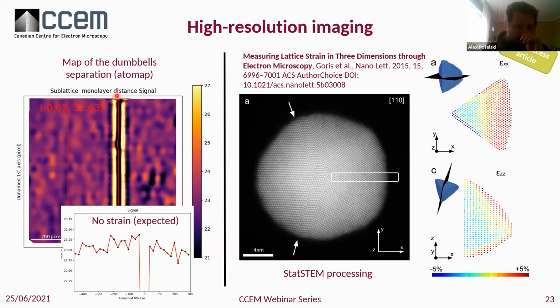On the other interface, this seems to be a big dip, so maybe there is a little bit of strain here. What you measure here, this intensity, is the number of pixels that is separating the two columns. This was around 23, and here is a little bit of variation. So to really conclude about the strain might be a little bit difficult. But as no strain was expected on that, I wouldn't consider it a measure here. It'll just be part of the noise.